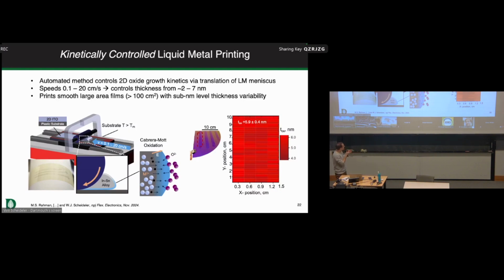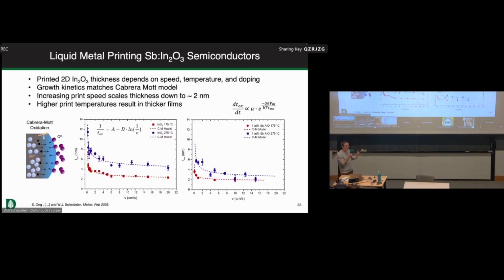Now, the process that governs this is Cabrera-Mott oxidation. It's the same process you might observe in the clean room. If Phil has mentioned this in class before, it's what happens to a silicon wafer when you leave it out and it grows that native oxide. Metal oxides form a little bit thicker layer, typically 2 to 3 nanometers thick, but it happens in the millisecond or even microsecond timescale. So if we're going to control it, we have to print fast, and that's the mechanism that we've been using. There are a few unexpected things.